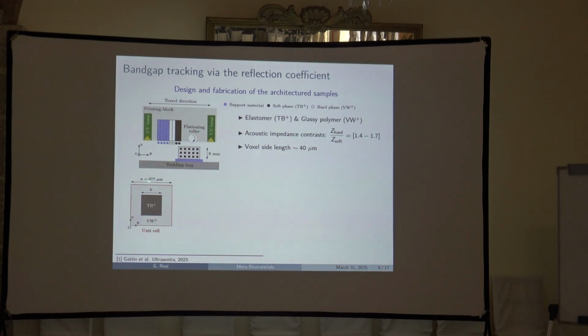And finally, we end up with this very simple geometry. The unit cell is around 700 microns. And inside, you have an inclusion of the soft material in the rigid material. This is what it looks like once printed at the microscope. So this is 1 millimeter. It's not perfect, but we will see that the thing that we are studying, let's say the band gaps, are quite robust with respect to this kind of imperfections.